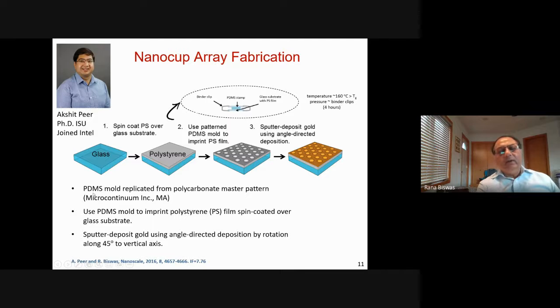We usually replicate these molds from a master pattern in polycarbonate. And we've had a very long-standing collaboration with this company, Microcontinuum in Massachusetts, that provides these master patterns to us. And then we imprint it on the PDMS mold. So then we use the PDMS mold to imprint the polystyrene film. And there are various conditions, high temperature and pressure, as you can see here, that help you to replicate the pattern, the inverse of the pattern.